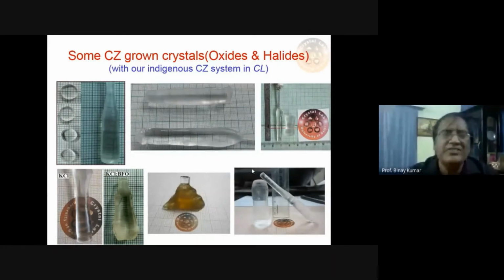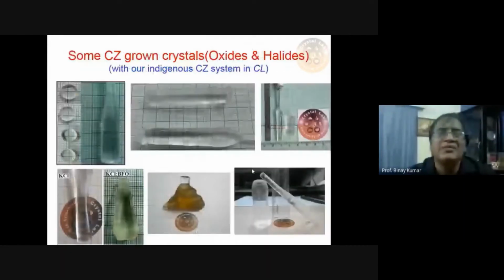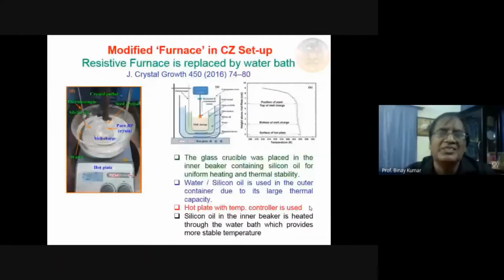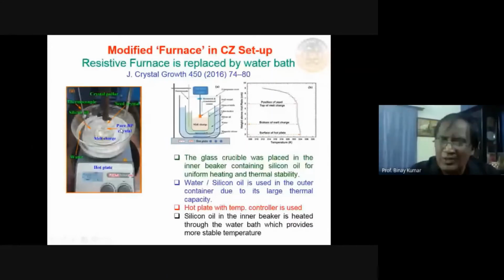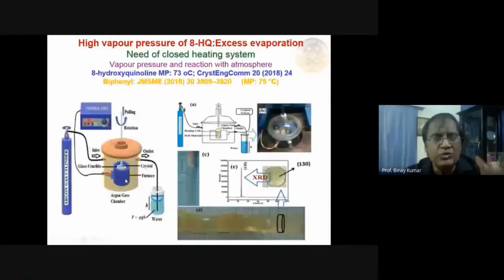Then this is one interesting contribution from our lab in the last 2-3 years. For growing organic crystals, this CZ method was never used; organic crystals are normally grown by the solution method. But we have introduced something, that we have replaced this whole furnace by a simple water bath. It is a beaker and water. I'm not explaining this, but with some modification in the whole system, using the basic concept of the Czochralski method, that we rotate the seed and pull the seed from the molten part, we have grown many organic crystals of this kind, which will be used later on.